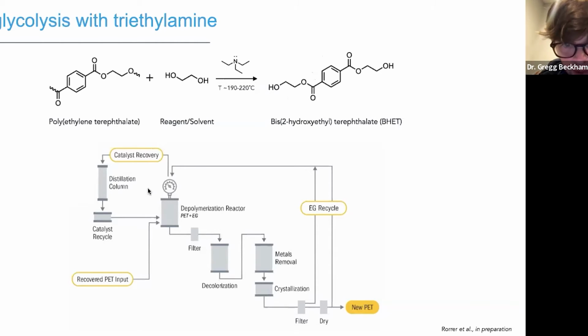And here is the process flow diagram that we're pursuing. We take recovered PET and put that into a depolymerization reactor. We filter out residual solids that are left over after the reaction, and do decolorization and metals removal over ion exchange and activated carbon columns. Then we crystallize BHET from that, which we can filter off and dry and then repolymerize into PET. Ethylene glycol is recovered and recycled to the depolymerization reactor.